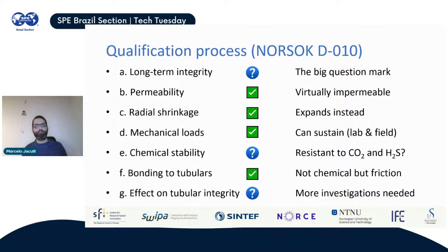And finally, the effect on the tubular integrity. Any alternative barrier material must not damage the tubular in which it's placed. This is something that still needs more investigation because we don't know yet the full effects of having this plug expanding inside the casing. It could damage the casing, it could damage the cement behind the casing, or for example, it could close cracks in the cement behind the casing. It could close microannuli between the casing and the cement behind it. So there is both the potential of doing damage and the potential of solving other issues. That's why I also believe this needs further investigation.